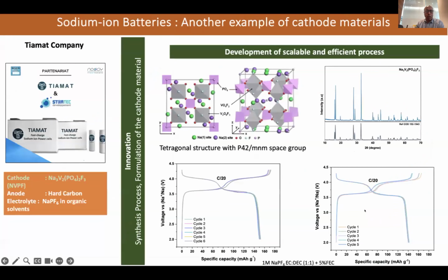I will finish with this one, which is very important. You know, the gigafactory Tiamat is using a cathode material using vanadium, phosphorus, and fluorine. And we developed our scalable and efficient process as an alternative. This is our approach. And you see here, we developed a good material, vanadium-based, but you see during cycling, we have 160 mAh/g, which is comparable to LFP with a low-cost material. And this is a good way to develop also in our laboratory.